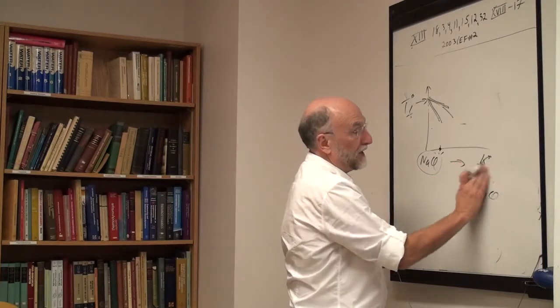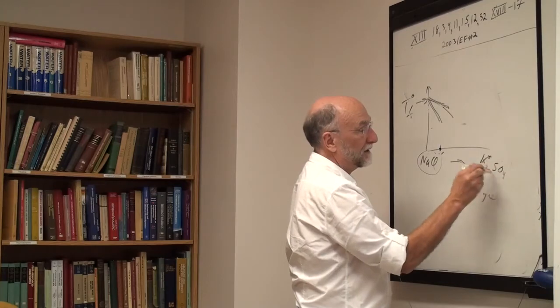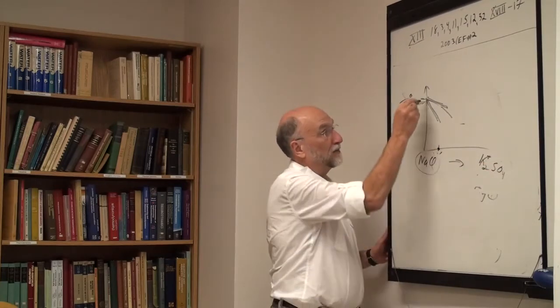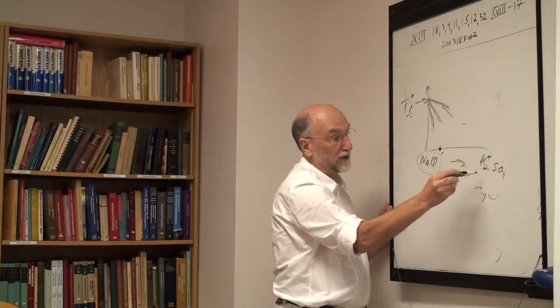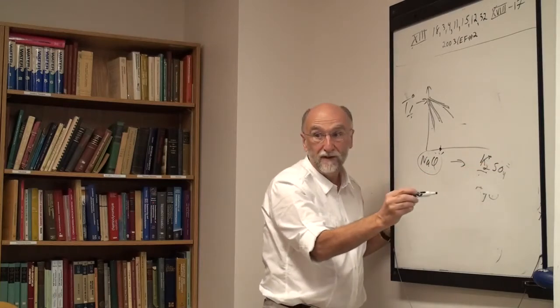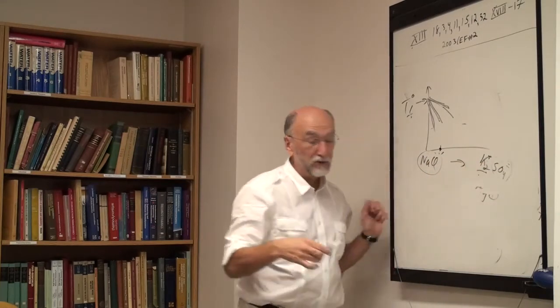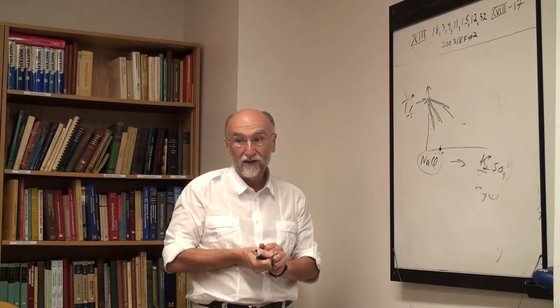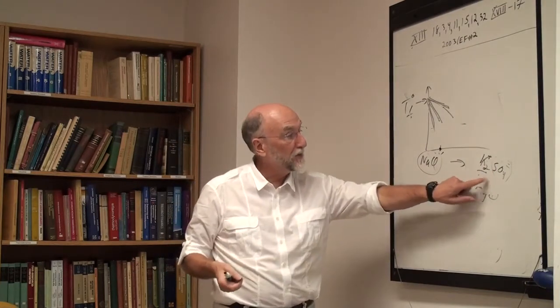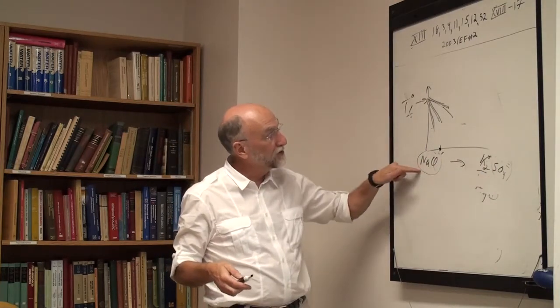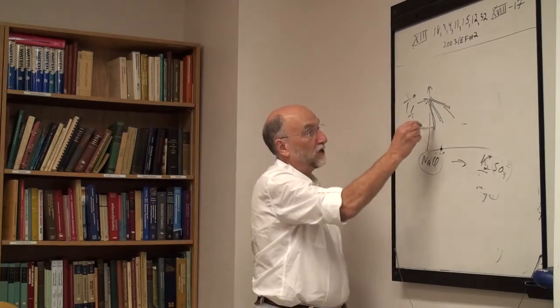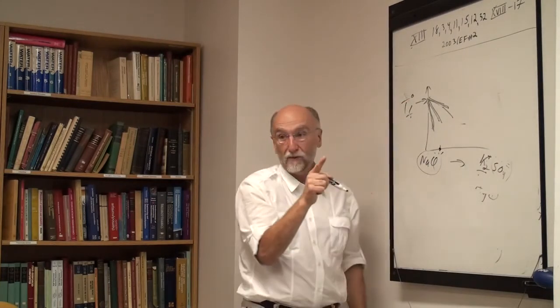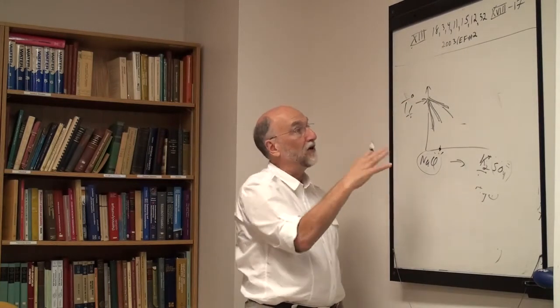If I were to add potassium sulfate, I would get a slope 3 times the slope because I got 2 potassiums and 1 sulfate. But the sulfate, of course, doesn't dissociate into sulfur and oxygen, it stays together. So once again, just putting K2SO4 in dilute solution in sodium chloride, I'll see the limiting slope will be exactly 3 times what I will get for 1 particle. And again, this is independent of all the excess terms.